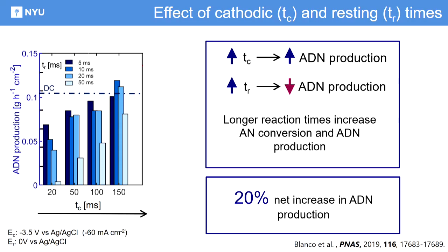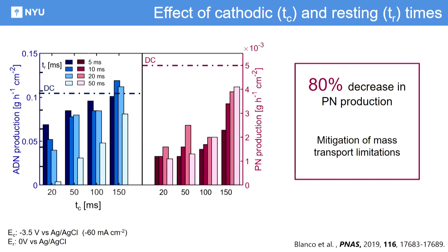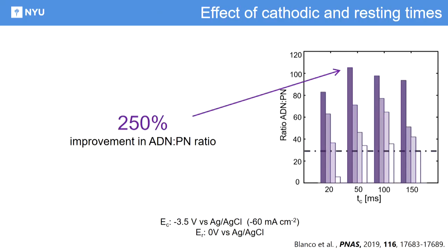And the reason for that is because you enhance the selectivity. So you reduce the production rate of your hydrogenated product, propionitrile in this case, and in that way allows you to reach a 20% improvement in production rate of adiponitrile and a 250% improvement in selectivity by controlling dynamically what is happening inside of your electrodes. So this is a classical reaction engineering trick applied to something that has already been discovered in terms of the catalysis and in terms of the chemistry.